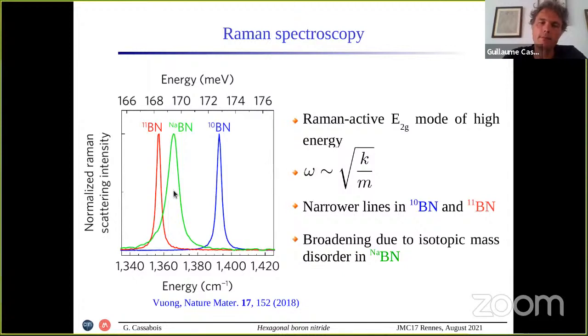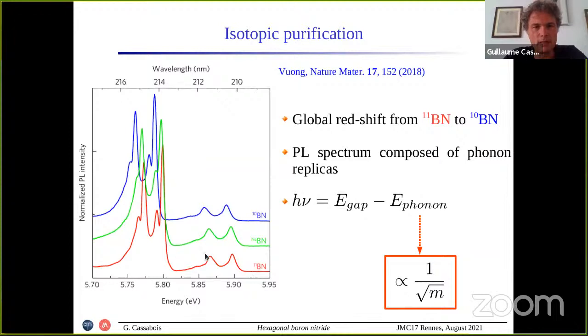We then perform PL spectroscopy. Now the scale is linear, so you may not recognize the spectrum I've shown before, which was in semi-log scale, but the effect is much nicer in this linear scale, where we have the emission of B11, B10, and B natural samples, showing the influence of isotopic purification. Remember that the photon has an energy given by the gap minus the energy of a phonon. So for the lighter isotope, B10, the phonons have higher energy, so the redshift is largest for B10. So we have this series of spectra, B10, B natural, B11, showing the effect of isotopic purification on the emission spectrum.